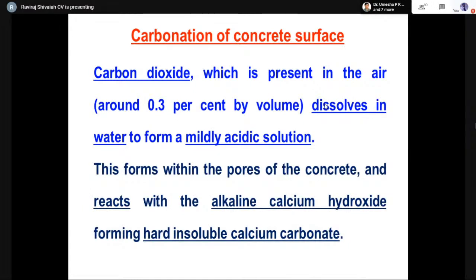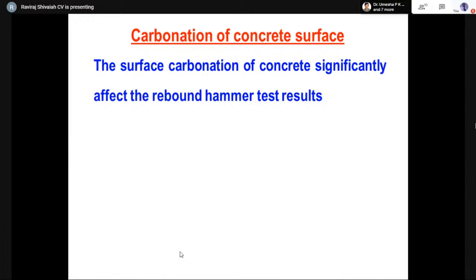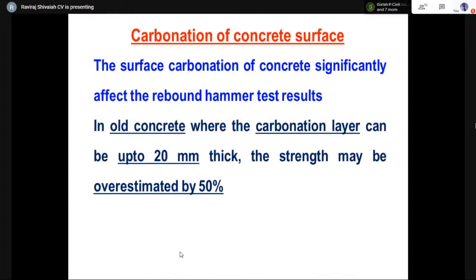Please understand, when we talk about the products of hydration, we have two important products: calcium silicate hydrate and calcium hydroxide. As we know, calcium hydroxide is unstable, not desirable. So there is a possibility that this mild acidic solution reacts with the unstable calcium hydroxide, which is basically alkaline, and forms a hard, insoluble calcium carbonate. So the reaction of the mild acidic solution with alkaline calcium hydroxide gives us hard, insoluble calcium carbonate. So the surface becomes hard, correct? And once we do a test on this hard surface, the rebound number will be quite high. And please understand that carbonation can progress up to 20 mm, an average estimate in very old concrete.